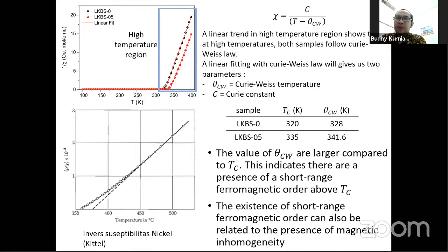And from the inverse of susceptibility, we found the Curie-Weiss temperature. What we can get from this is that the value of the Curie-Weiss temperature is larger compared to TC. For example, for the LKBS 0, TC is 320 and the Curie-Weiss temperature is 328. Also in LKBS 05, TC is 335, but the Curie-Weiss temperature is 341.6.